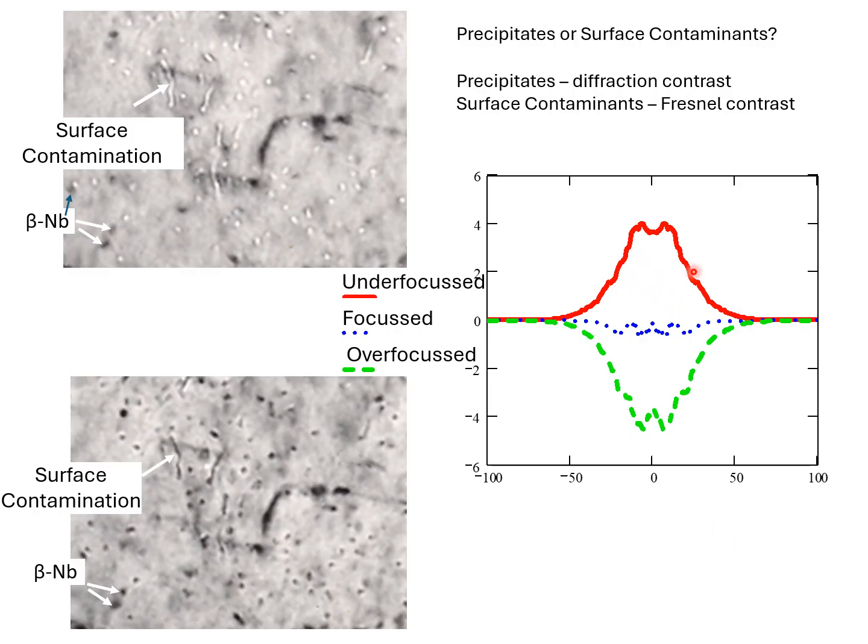If we vary the distance slightly, like a fraction of a nanometer, in this particular case, we go from a condition where we have a bright peak, like here, or a bright image, to a dark image, as we have here. And at the point of focus, if you like, there is very little intensity.